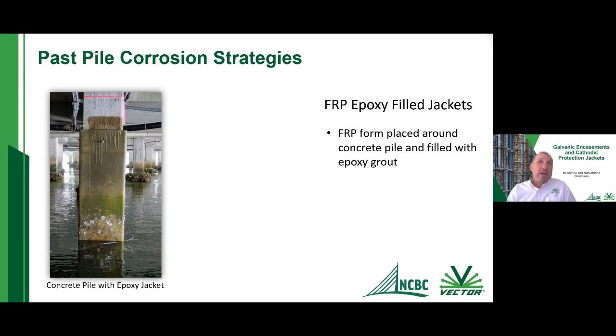So another one is the fiberglass jacket. Basically it's a fiberglass jacket that is placed around a pile, and then it is filled with an epoxy grout. The hope is that you would put the fiberglass jacket around with the epoxy grout, and reduce the amount of chlorides and the amount of oxygen to that portion of the pile.